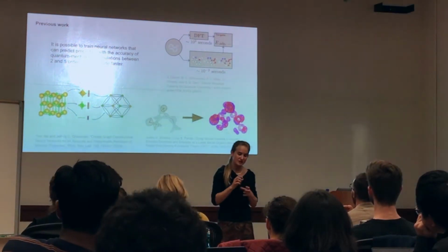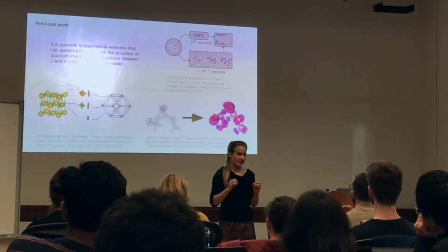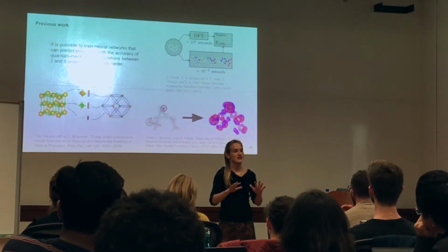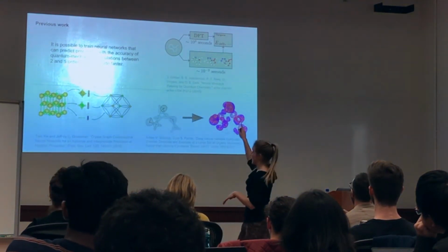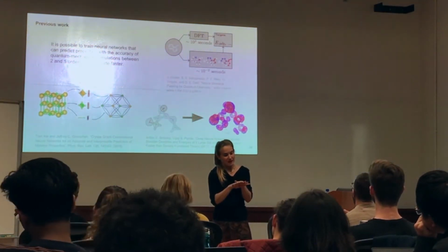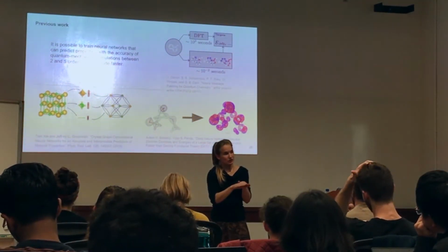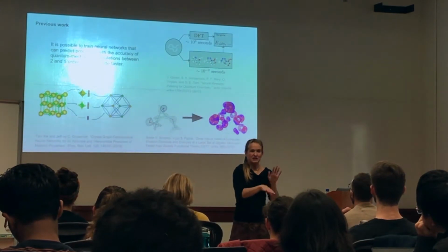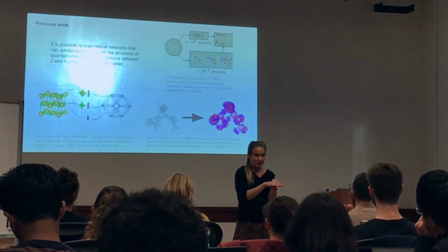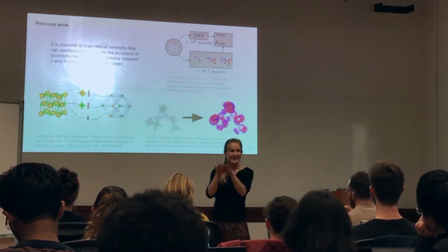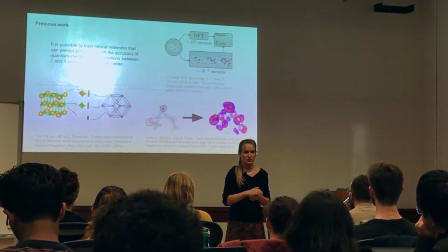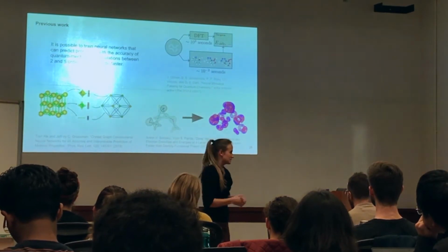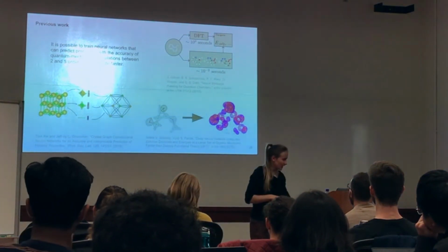So they would use a very cheap quantum mechanical calculation to calculate the electron density, so where the electrons are at, for actually the same QM9 data set that the top paper used. And then they would train a neural net to take that kind of low-level theory charge density and convert it into a high-level theory charge density. So basically, refine it according to a higher level of theory functional. So that's sort of interesting.